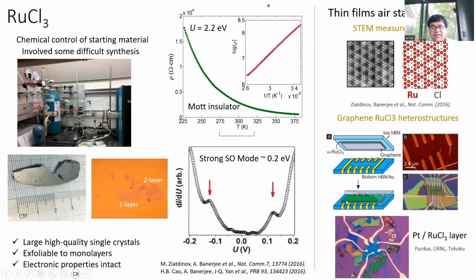excitations. So we have a large amount of experiments that we have done, including scanning tunneling spectroscopy measurements. We have done several thin film measurements. We have excellent data on platinum, ruthenium chloride heterostructures with Yongchen's group, where we have looked at those excitations not using neutron scattering, but using spin Hall magnetoresistance for platinum. So that's a paper that is hopefully going to come out very soon in Proceedings of the National Academy of Sciences. And so we have a lot of work going on here. We will be mostly talking about the neutron scattering results, though.